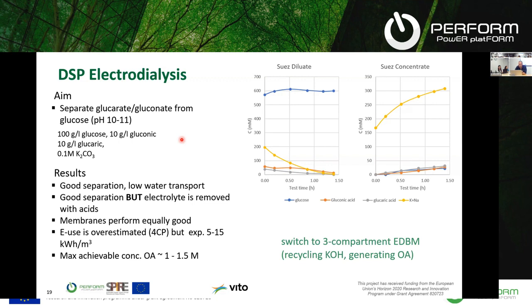Membranes perform equally well in the sense that we tested a range of membranes from different suppliers, and also had an estimation of the energy usage during operation of the electrodialysis. But in order to overcome the issue of electrolytes, which is actually spent together with the gluconic and glucaric acids, we switched to a 3-compartment electrodialysis, so not a conventional one, but a 3-compartment with a bipolar membrane, which allowed us on one side to separate the acids, gluconic and glucaric, together in an acidic compartment at their natural pH, let's say, and on the other end also recover the alkaline electrolyte, so the potassium hydroxide in this case.